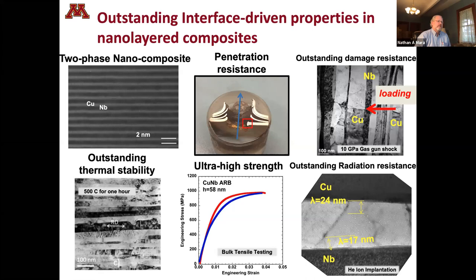Same thing goes for outstanding radiation damage resistance. You layer this material up and you'll have regions close to the interface that absorb radiation-induced defects. And so you can essentially make a material that heals itself as it is either pulled or pushed in different ways or irradiated. This material ends up being very, very robust.